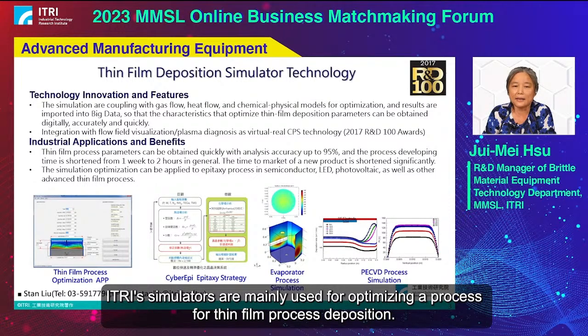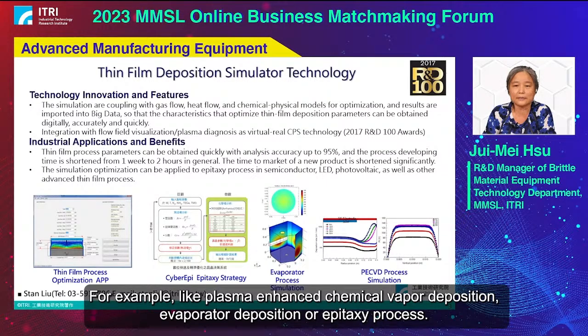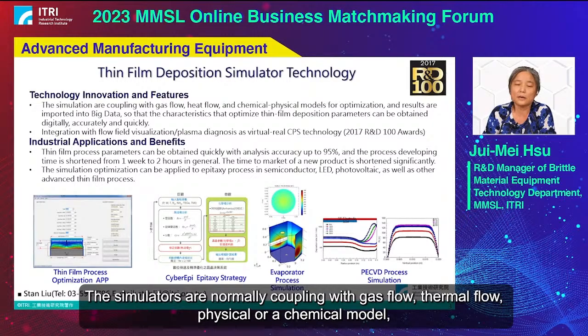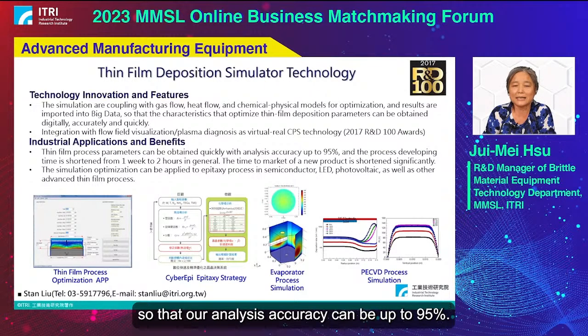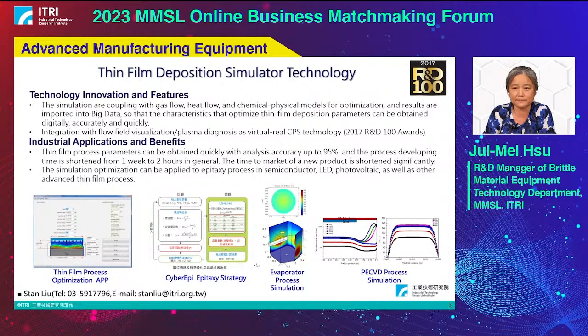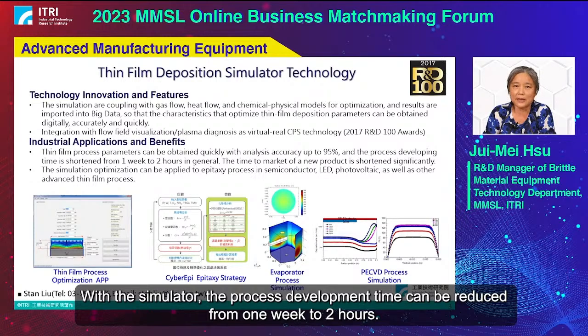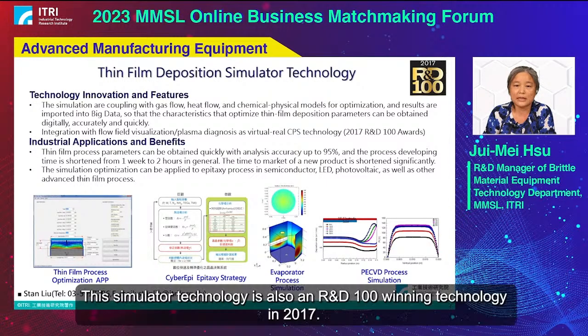ITRI simulators are mainly used for optimizing processes for thin film deposition, for example, plasma-enhanced chemical vapor deposition, evaporator deposition, or epitaxy process. The simulators are normally coupled with gas flow, thermal flow, and physical or chemical models, so that our analysis accuracy can be up to 95%. With the simulator, the process development time can be reduced from 1 week to 2 hours. This simulator technology is also an R&D 100 winning technology in 2017.